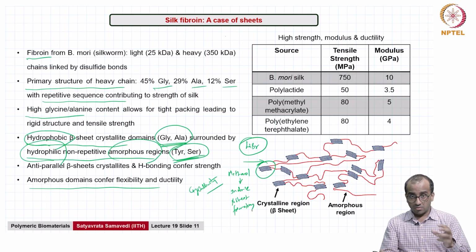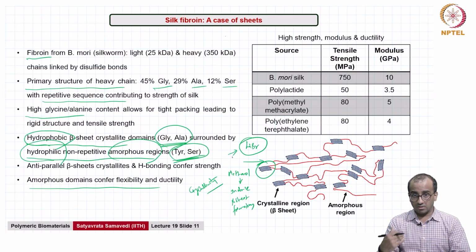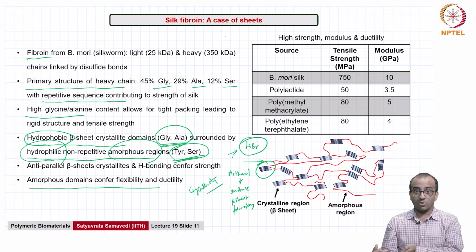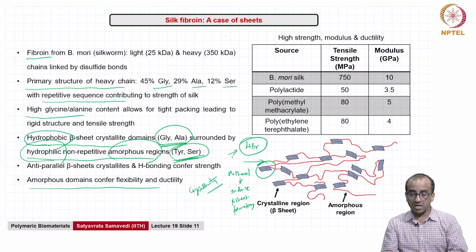So, the original silk that was water insoluble, through the lithium bromide treatment and a series of processing steps, has become water soluble, and then once it is processed, you can again induce the beta sheet formation, induce crystallinity through methanol treatment. All of it has to do with how these chemicals, reagents interact with the hydrogen bonds and how they disrupt the secondary structures in silk.